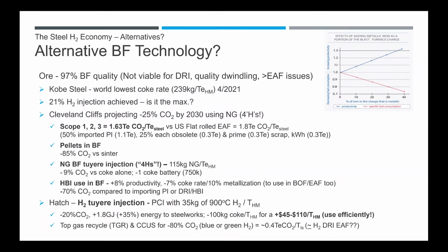Now, if you add top gas recycle and CCUS to that, he's anticipating 80% reduction in CO2 if you use the blue and green hydrogen, and that equilibrates. Hatch is saying to hydrogen DRI in the EAF at 0.4 tons of CO2, but technically that can be as low as zero. Next, please.